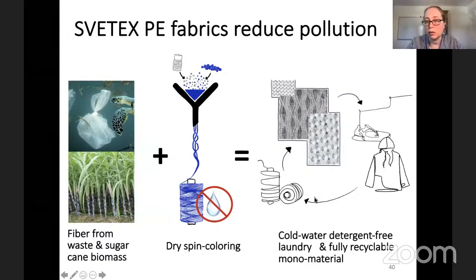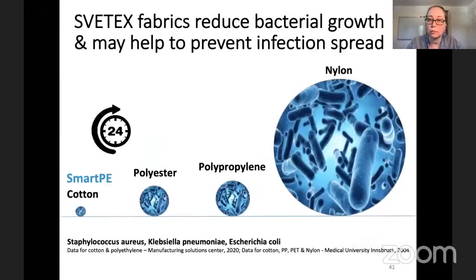And that leads us to this monomaterial closed loop material cycle, which produces significantly less pollution at every step of production and use. And also through testing, we found that it actually prevents growth of bacteria naturally without even adding any antibacterial addends to it. If you measure in 24 hours how much bacteria will grow on different fabrics under identical conditions, it's just shown schematically by the size of these circles.